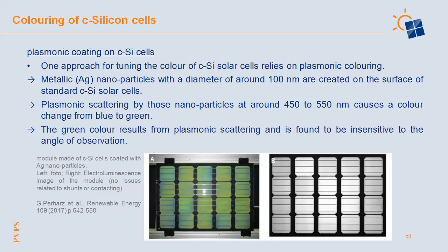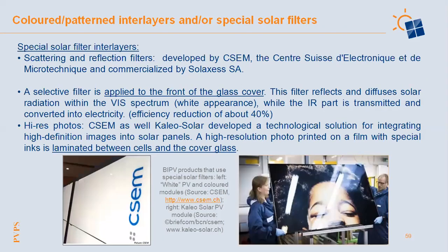The nice thing with this system is that you have a very high insensitivity to the angle of observation. Then the next possibility is to use colored or patterned interlayers or special solar filters. With this technology, CSEM, the Swiss Center for Electronics and Microtechnology, had two projects showing really white BIPV products. They used a very special scattering and reflection filter on the surface of the front glass cover, but at the expense of an efficiency reduction of nearly 40%.